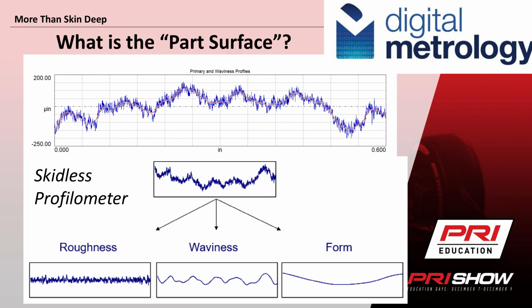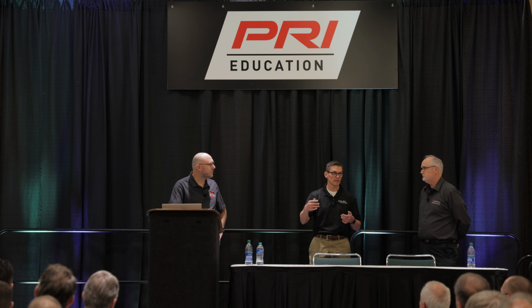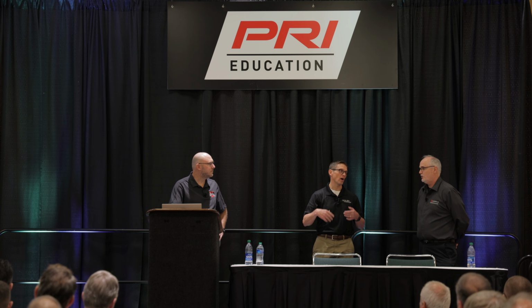Now, if you had a skidded profilometer, there's a water ski up underneath the diamond, and so you don't see the form or the waviness, you just see the roughness. There's a lot of information there, but remember, it's only 1/3 of what we talk about when we're talking about surface texture. And this is really big for decks. We're talking about gaskets and that kind of stuff. It's easy to use the skidded profilometer on a bore and get the information that you need. But when you're talking about waviness on a deck, it's going to be really hard to see that. And that waviness on the deck is what's going to cause the leaks. Yeah, exactly.